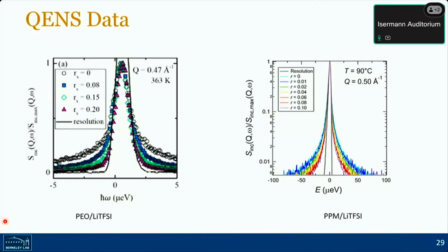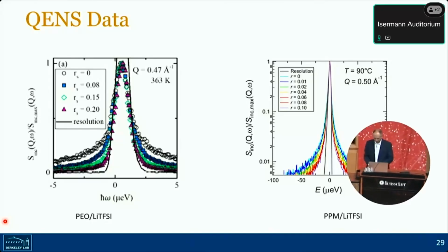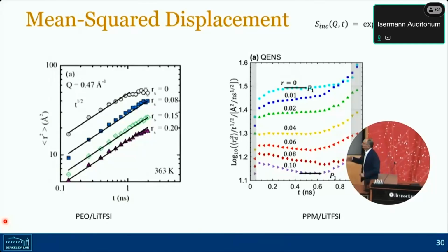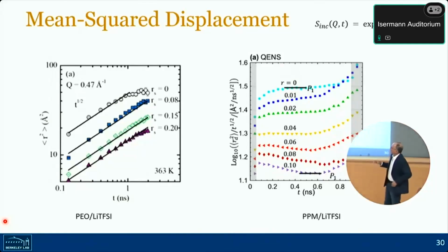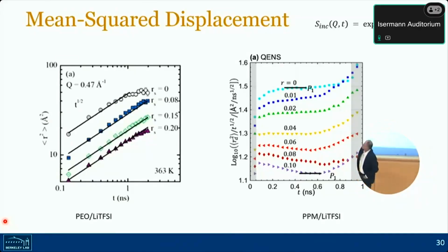You can take these things and get at exactly what I was talking about, which is the mean square displacement, at a certain scattering vector, a certain angle. I wanted to first tell you that the mean square displacement is in the 5 to 50 angstrom squared range, and the time is 0.1 to 1 nanosecond, okay? When we talk about molecular dynamics, there's a lot of talk about what the structure is, but very seldom do you get to analyze how quickly things are moving. And I don't know that there's anything else that is quite as robust as quasi-elastic neutron scattering for that purpose.